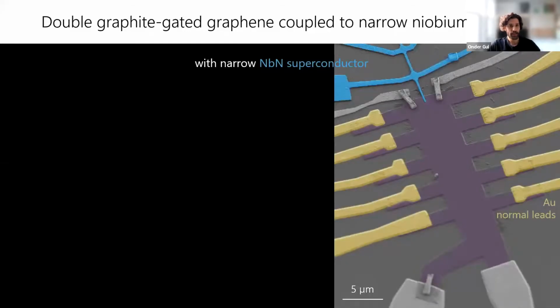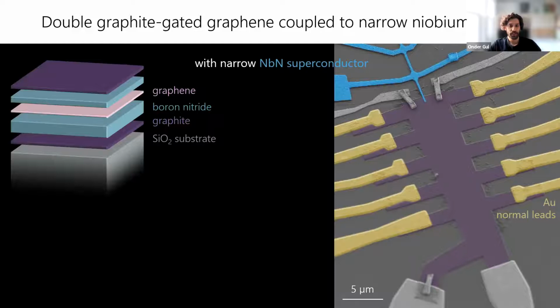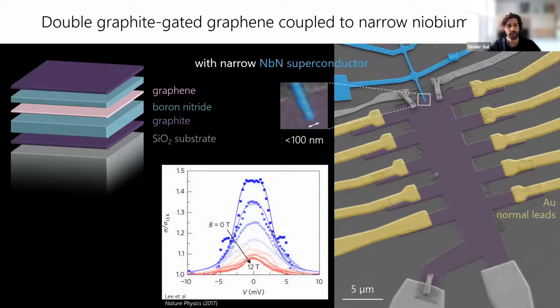Let me immediately start by introducing the experimental system, which is a double graphite-gated graphene heterostructure. Double graphite geometry screens remote impurities and so increases the mobility. The resulting decrease of the magnetic field range for stabilizing fractions allows for simultaneous observation of superconductivity. The heterostructure is transparently coupled to a narrow niobium nitride superconducting electrode. Here, you can see the Andreev conductance enhancement of this geometry shown in the initial work.